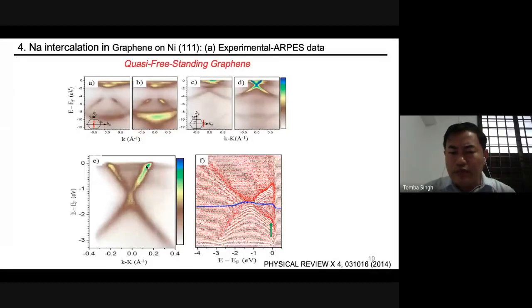Now, let's discuss the kink just below the Fermi level. If we draw the momentum dispersion curve, this is the curve of different intensities at different wave vector versus energy. Following the wave vector at the Dirac point, we see no appreciable band gap, represented by this blue line. But just below the Fermi level, around 200 millielectronvolts below, there is a kink. There are many reports about this kink. They explain that this is due to electron-phonon and electron-plasmon interaction. From that, the band structure is renormalized and this kink comes out.